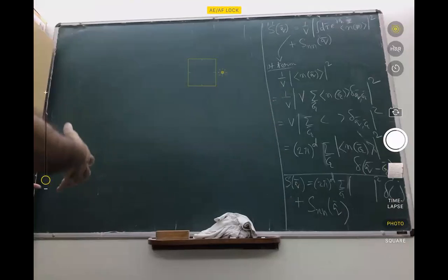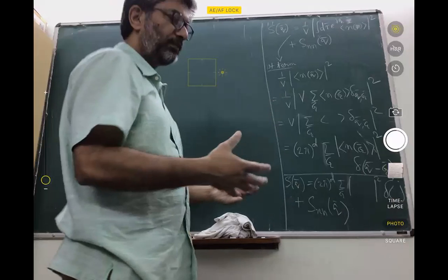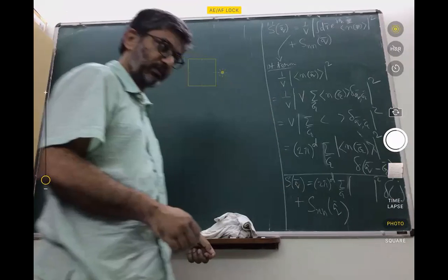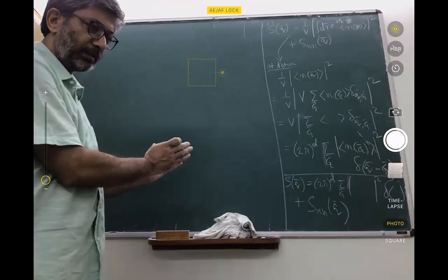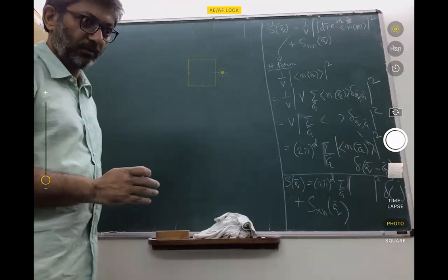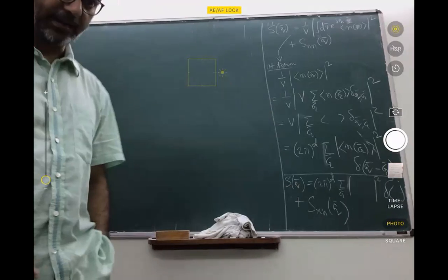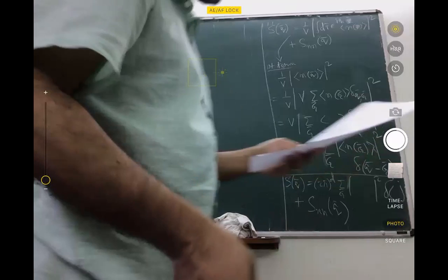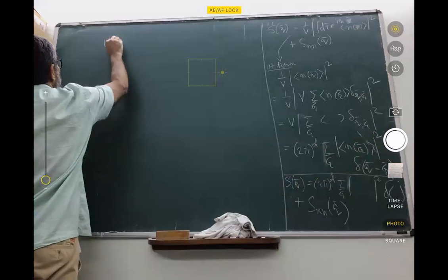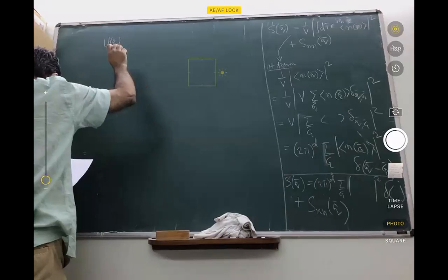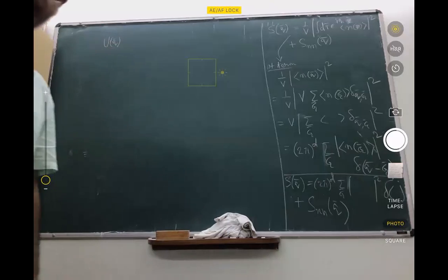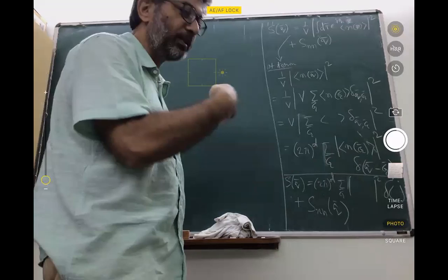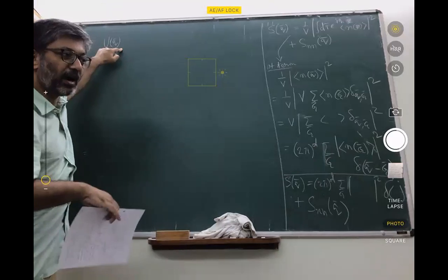One contains information about the arrangement of the atoms, which is captured by this structure factor, and the other depended on the potential of scattering from the atoms. Okay, so that U part. I just want to remind you of that. So this potential U is what the scattering particles experience when they scatter. I mean, it's the potential because of which the scattering particles undergo a scattering inside the material.